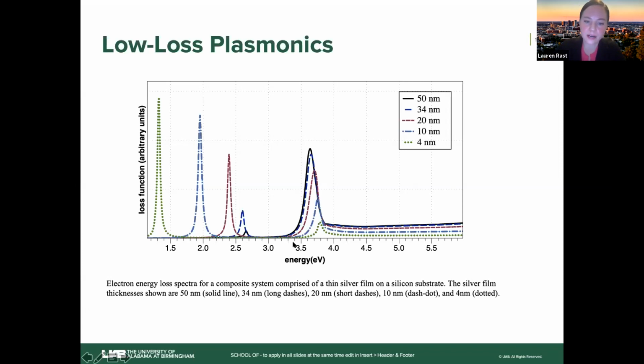We have this higher energy peak and a lower energy peak. This isn't the zero loss peak that I'm going to show when I talk a little bit more about spectroscopy. These are surface and bulk peaks. Okay, so one way to couple more strongly, as I said, to these surface modes is just to make your layers thinner and thinner, and you can see a dramatic effect as we go down from 50 nanometers to 4 nanometers for these silver films.